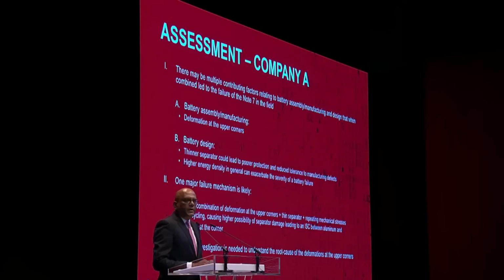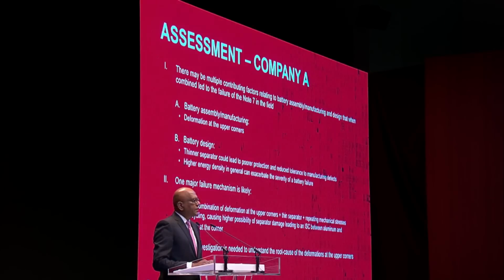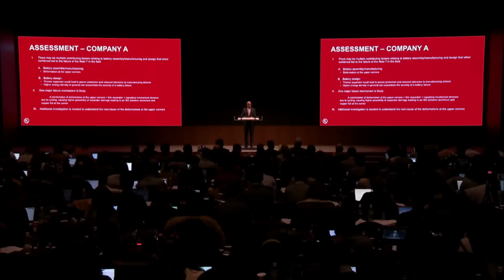Our assessment for Company A further suggests one major failure mechanism for the likely possibility of a field incident. This was a combination of the deformation at the upper corners, the thin separator, plus the mechanical stresses due to cycling, which causes the possibility of separator damage, leading to an internal short circuit between the aluminum and copper foil at the corners. Additional investigation is needed to understand the root cause of the deformations at the upper corners of the batteries.